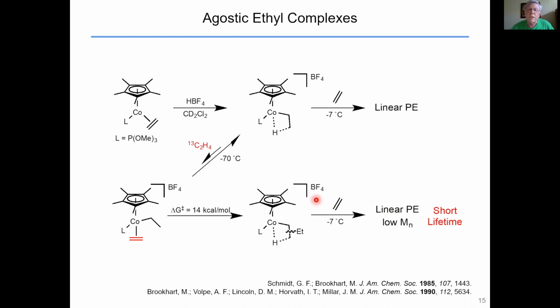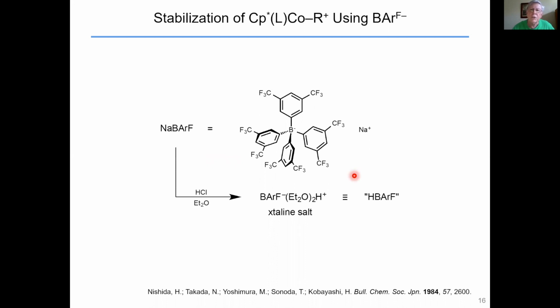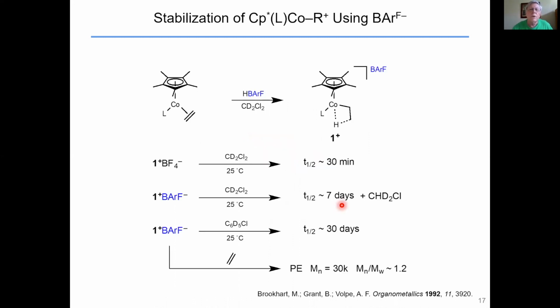And we proposed that the lifetime was limited by the counterion. BF4 was known at that time to be a fluoride source. And so we expected that this highly electrophilic cobalt-3 species was simply being quenched by BF4. So we sought out a more unreactive counterion and decided to use this Kobayashi counterion, which you probably now know as the BARF counterion, this tetraaryl borate species sprinkled with CF3 groups. And we were able to make an acid of that species by simply taking the sodium BARF, treating it with HCl and ether, and generating the etherate BARF salt. So using that acid, we could generate the cobalt species with the BARF counterion.